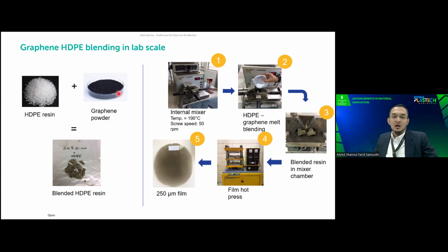We blend the graphene powder with the HDPE resin. But before we do this blending, we do some treatment on this graphene. We put it in the solvent to prepare as a master batch, and we let the graphene exfoliate first and then disperse well in the HDPE pellet. And after that, we conduct the melt blending using an internal mixer.